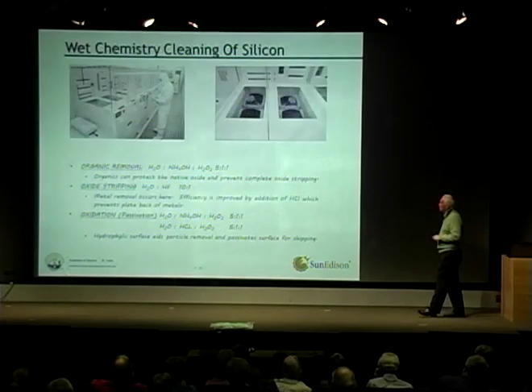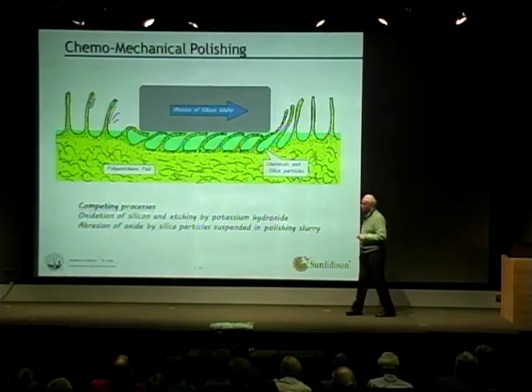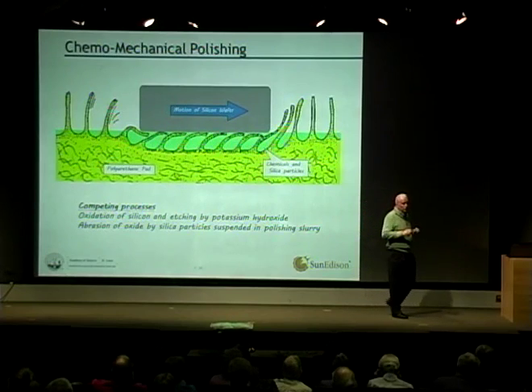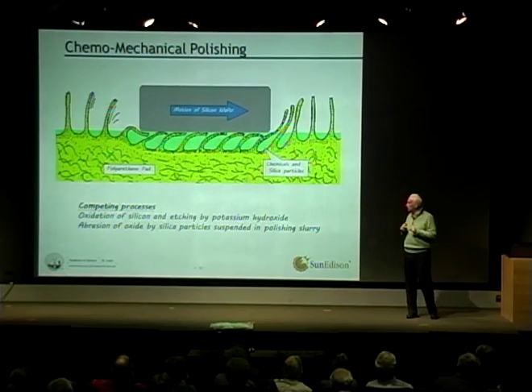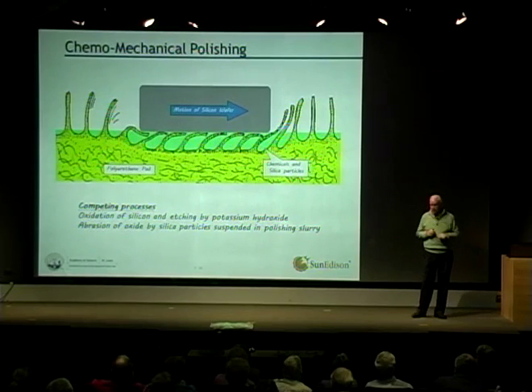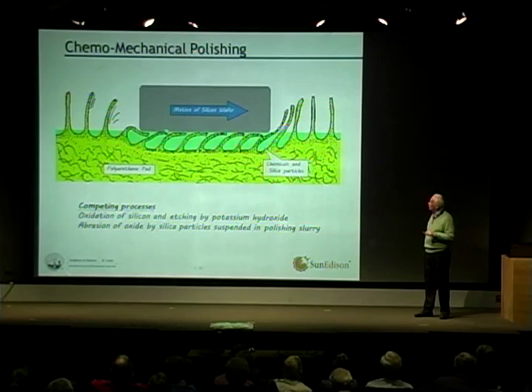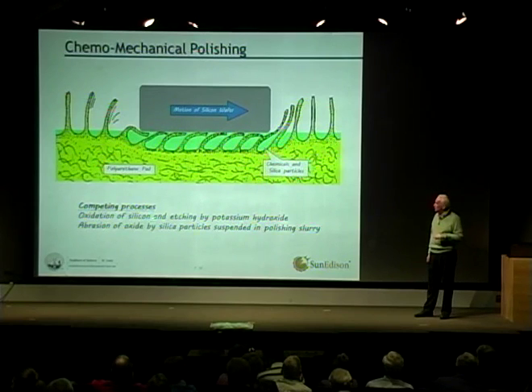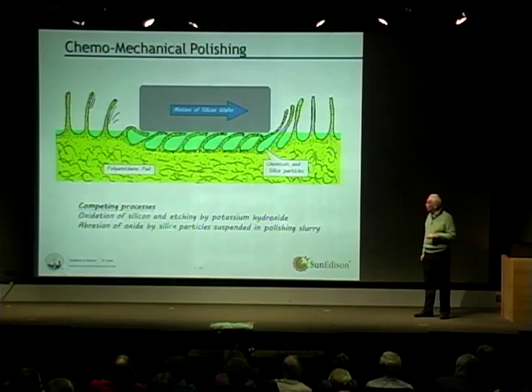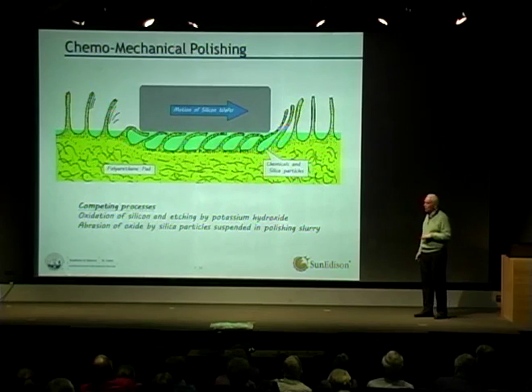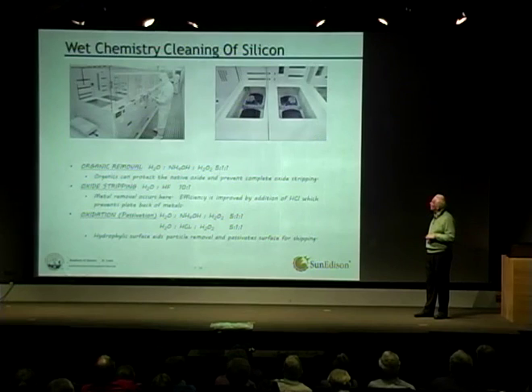So there are competing reactions. It's called chemomechanical polishing because it's a mixture of chemical and mechanical polishing. What's going on is the potassium hydroxide is etching the silicon. But there's water present as well, and the water has oxygen, so it oxidizes the silicon. So you have an oxide layer, and the oxide layer is abraded away by the silica particles that are in the slurry. So the mixture of the chemical part, potassium hydroxide etching, and the mechanical part, the silica particles abrading the oxide. These two reactions compete, and they gradually wear down the silicon and make it very smooth and shiny. I'm going to try and speed up a little bit here now.